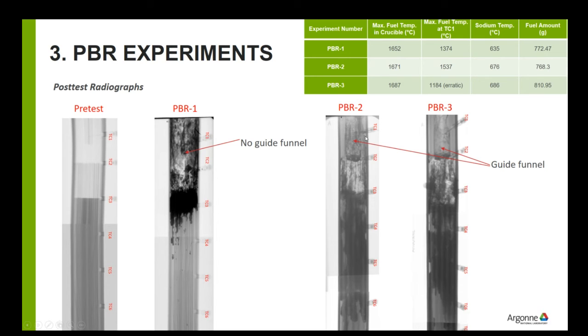So after the PBR2 experiment, we wanted to try to localize the injection of the fuel into the coolant channel, so we coated yttrium oxide on the internal surface of the cladding to limit the amount of eutectic formation. But the injected fuel was still the uranium-iron eutectic, so the fuel can still flow much further than in PBR1, but slightly shorter than in PBR2.